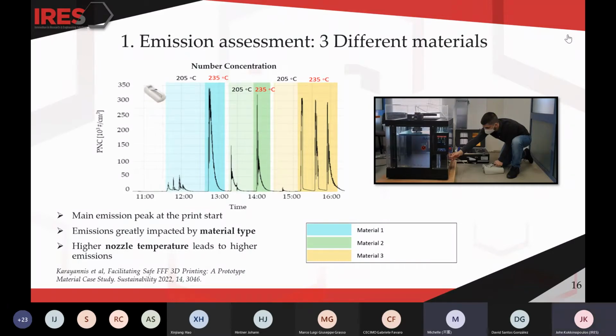During the first campaign, you can see that a commercial 3D printer was used and 3 candidate prototype filament materials were evaluated in terms of their comparative ultrafine particles emission potential. The impact of nozzle temperature on the magnitude of emissions was the main parameter evaluated. As we can see from the diagram, each color corresponds to a different material, and the different nozzle temperature settings used for printing each of these materials can also be seen.